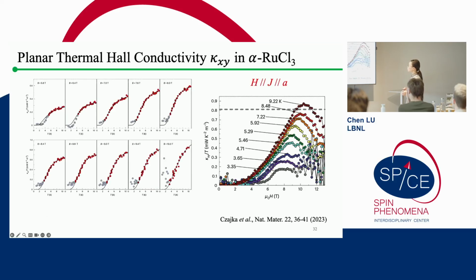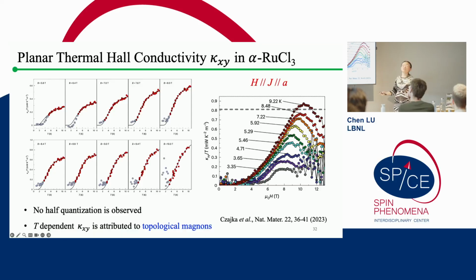And later on, Professor Huang's group tried to reproduce exactly the same planar thermal Hall effect measurement with the same configuration. They also saw a non-zero planar thermal Hall effect that shows up at a different field and different temperature. But the one thing is, here you can see there is no obvious half-quantization observed. And also their theoretical interpretation was different, which comes from some topological magnons or chiromagnons related to this Kitaev material. Okay, so this was the very first study of the so-called planar thermal Hall effect in an insulating material.